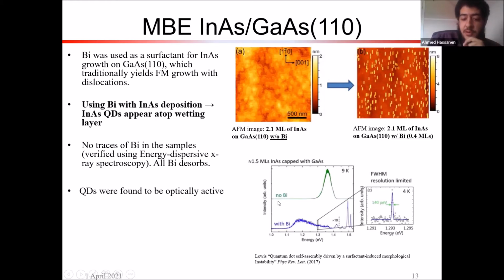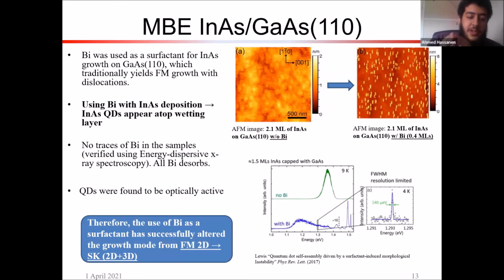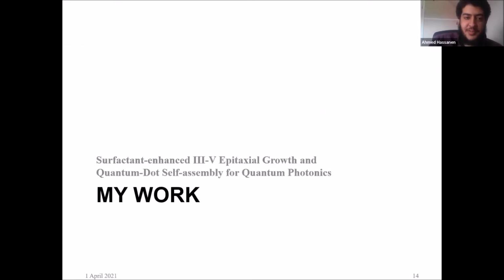You can see here the photoluminescence done without bismuth. You just get a response of probably the wetting layer. And then with bismuth, you start to see these sharp transitions, which are indicative of optically active quantum dots. The takeaway here is that bismuth has been used as a surfactant on 110, and it has successfully induced a change from the 2D to the SK growth mode. So we know it works on this surface.